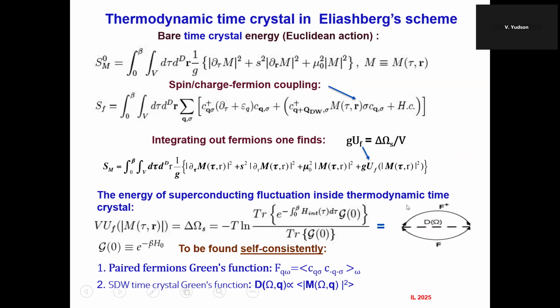And then this loop, in order to make it negative, the order parameter should be D wave. Because here, one electron has spin up, one electron has spin down. So if it is spin singlet superconductivity, in order to make this loop negative, the vector Q, this density wave vector, should connect regions of the bare Fermi surface with opposite signs of the superconducting order parameter. And this is indeed found in the high Tc cuprates.